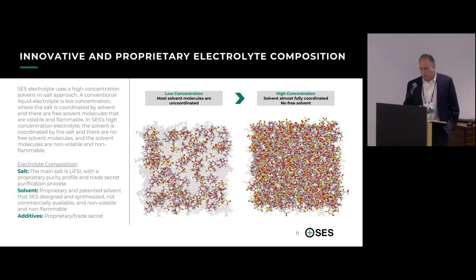So we have an innovative and proprietary electrolyte. It's a high concentration solvent-in-salt liquid electrolyte. It's kind of the opposite of the electrolyte that you would find in a conventional lithium-ion battery today. The solvent is coordinated by the salt. There are no free solvent molecules, and importantly, the solvent molecules are non-volatile and non-flammable.